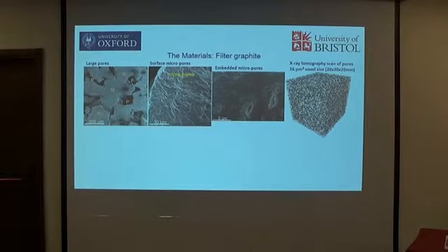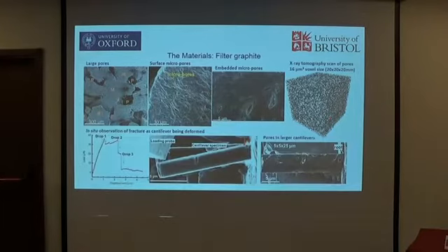But if you look into the matrix, there are micropores, and that's a big cross-section to see into the volume. It is not solid. It then has micron and submicron porosity. So that is a tomography scan of a 20 by 20 by 20 millimeter cube. So that is the porosity structure of the sample.